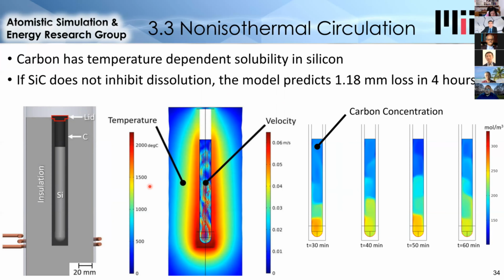The way I tested this simply was just to use a tall tank and heat the bottom of it to induce natural convection. So the bottom of the tank was about 500 degrees hotter than the top. This causes silicon to heat up and become less dense, float to the top, then cool off and float back down. This results in circulation from the hot zone to the cold zone. And when I apply a mass concentration boundary condition based on the solubility of carbon and silicon, this model predicts, like I said, the 1.2 millimeter loss over 4 hours.